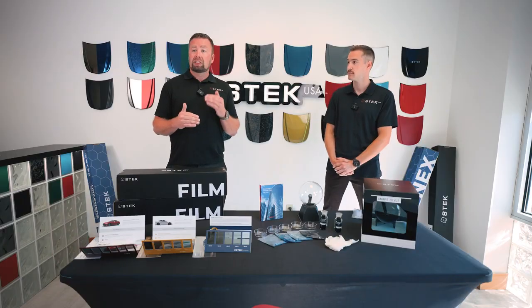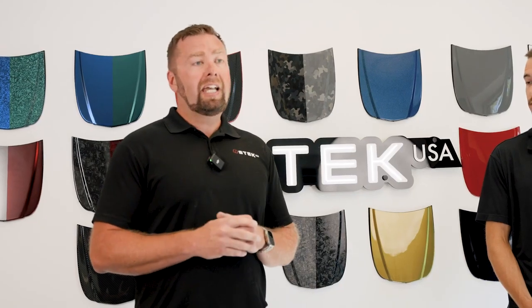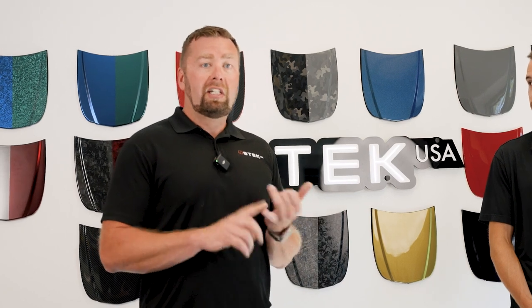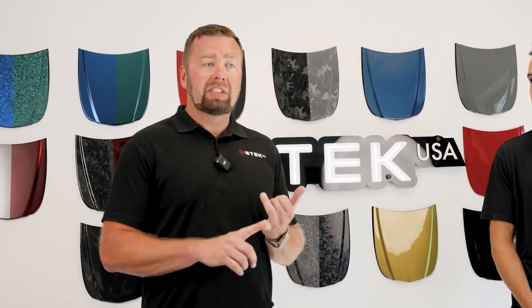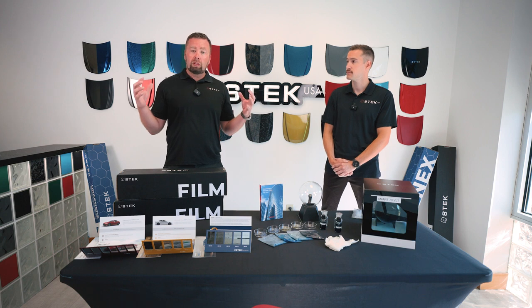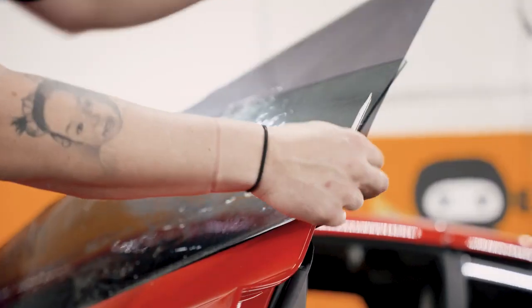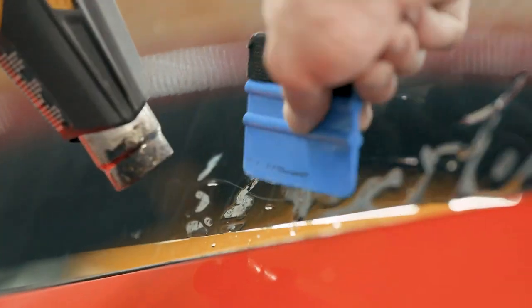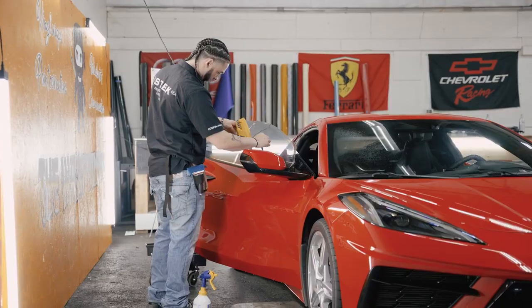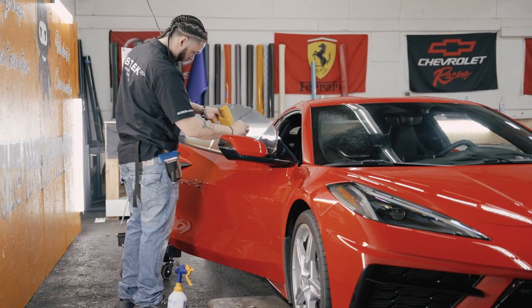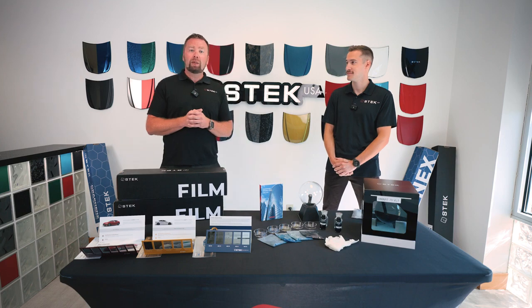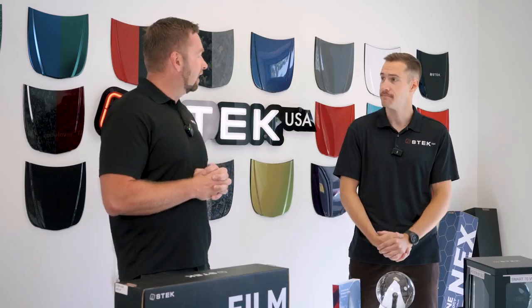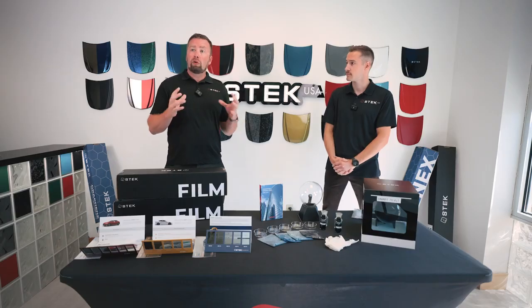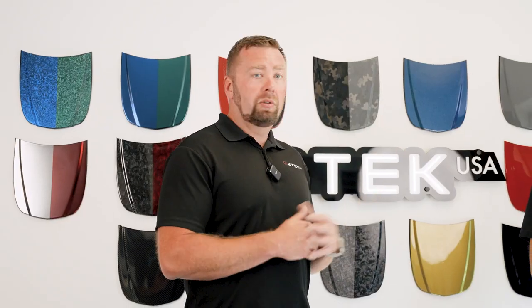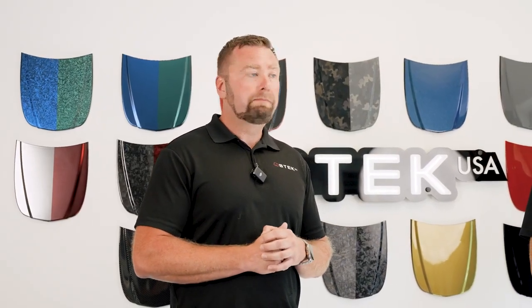So when a film is recycled, it's heated, and this can not only cause haze and distortions in the film, but also it will pre-shrink the material. That means when we go to shrink it to fit on your vehicle, we can sometimes be out of shrink, meaning we don't have enough manipulation. Exactly, yeah, in that product to be able to conform it easily onto a vehicle with very curved glass.